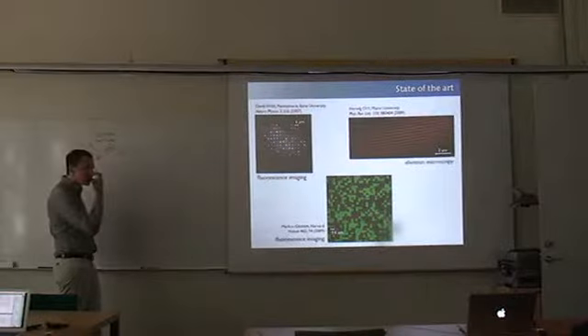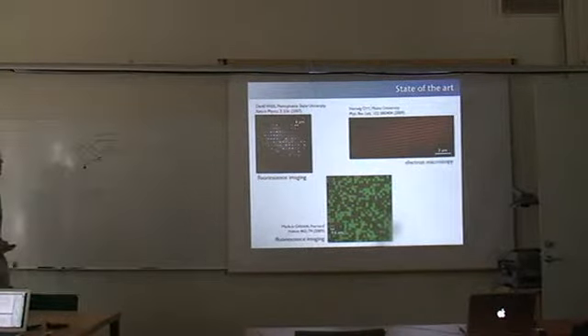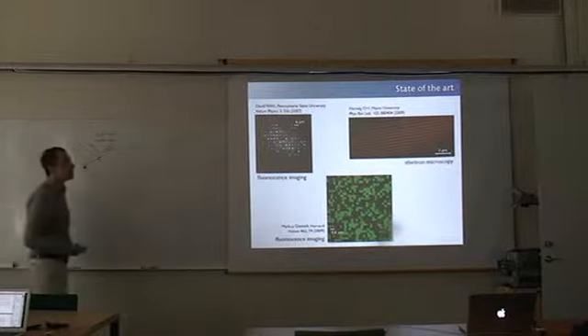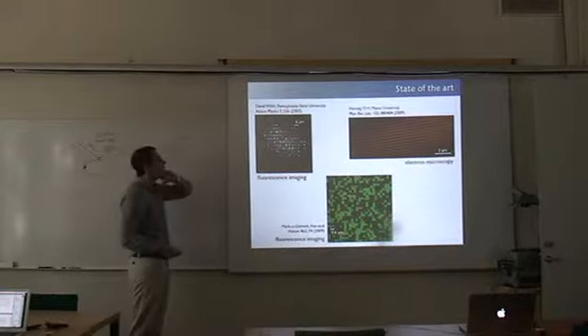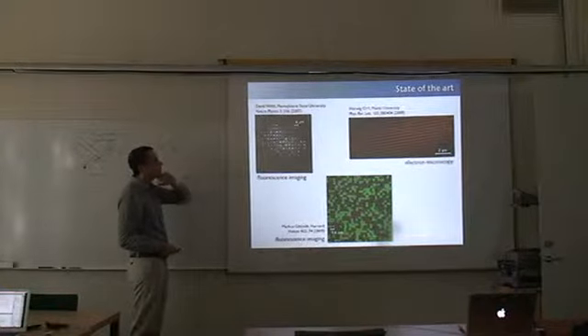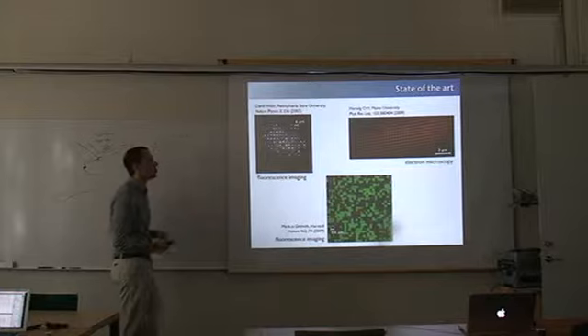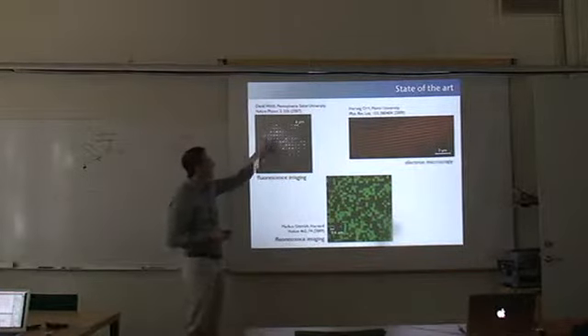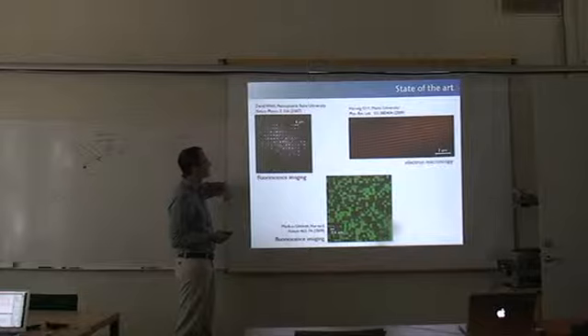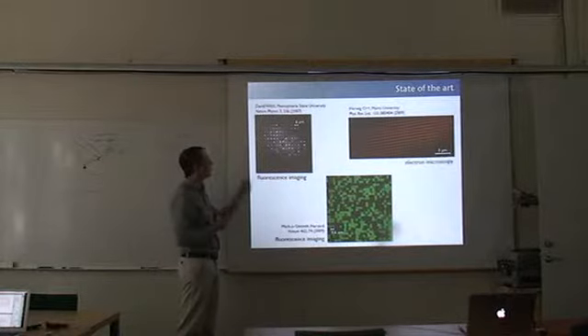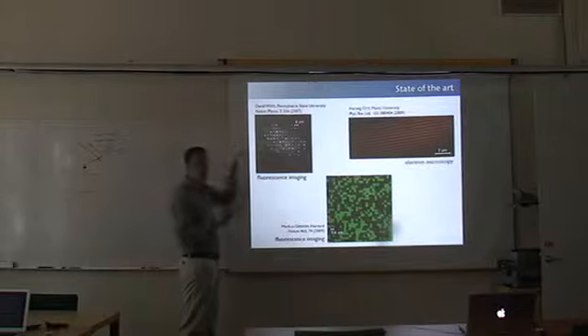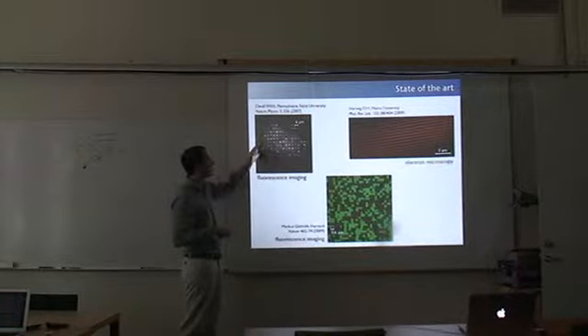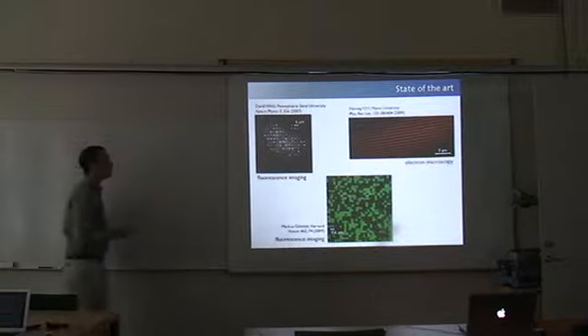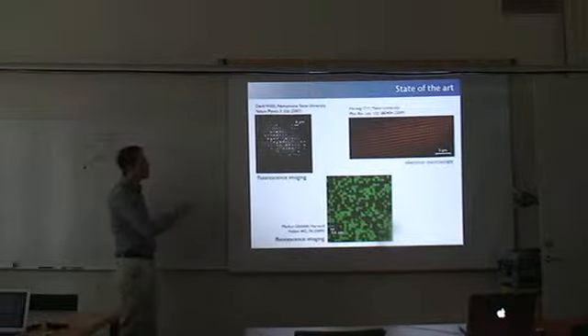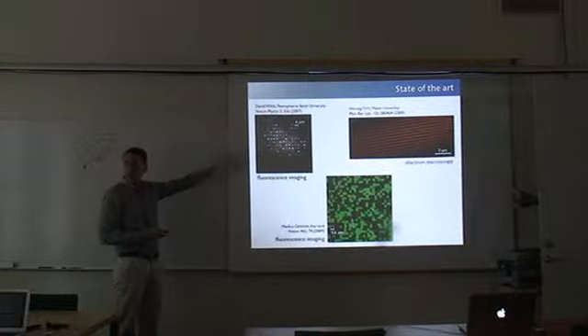So let me go a little bit into this and tell you about the history of this single site imaging. There are basically different methods that people use. The most intuitive way was first pioneered by Dave Weiss' group at Penn State, where they loaded atoms from a hot gas, not a quantum degenerate gas, into a very large spaced lattice with 5 or 6 micrometer spacing, and used fluorescence imaging to make the atoms fluoresce. You just shine in laser beams. Each atom now fluoresces. It's like a small light bulb. You capture that fluorescence with a high resolution microscope objective, and then you can see these individual atoms. These are the first pictures from his paper in 2007, where he could see single atoms in the lattice, each bright spot being a single atom.